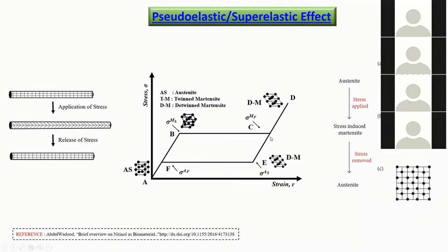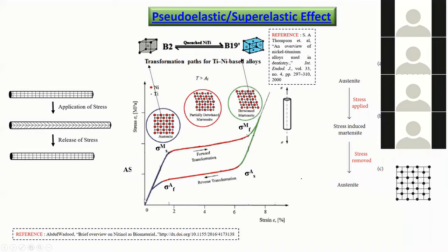And then we remove the stress. It comes back through the martensite and the detwinning process and returns to the austenite, the initial phase itself. Okay, so the entire strain is completely recoverable, similar to elastic recoverable strain, and is often known as super elastic. So it's elastic to a very high extent, or pseudo-elastic. It looks like elasticity, but of course it is not because of elasticity; it is rather because of the reversible phase transformation that is happening.